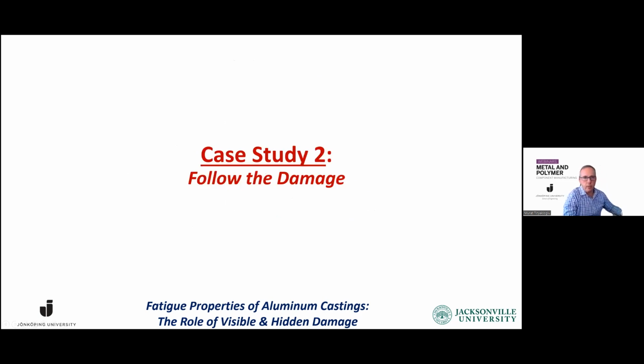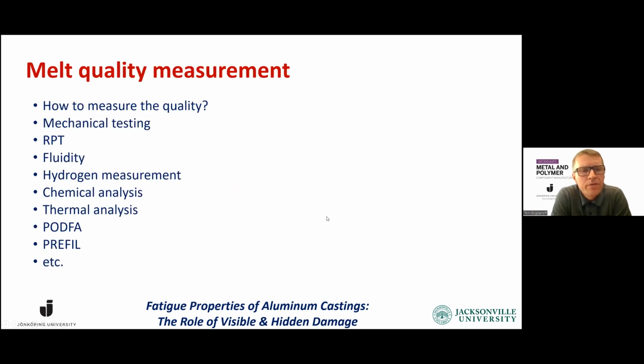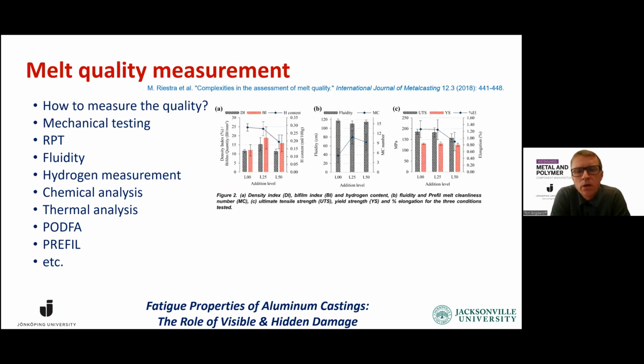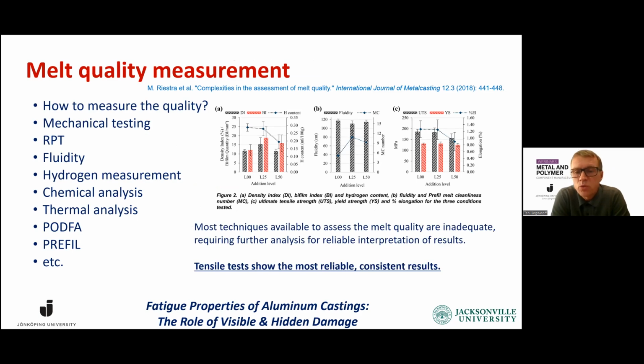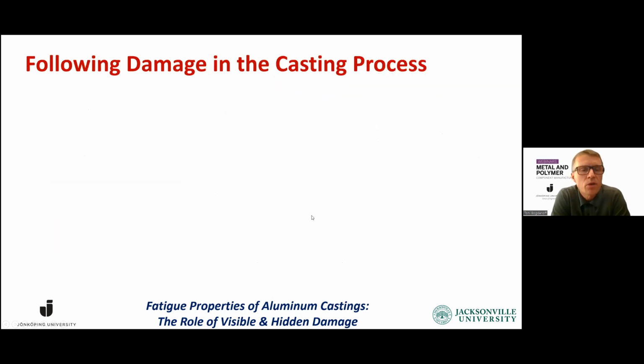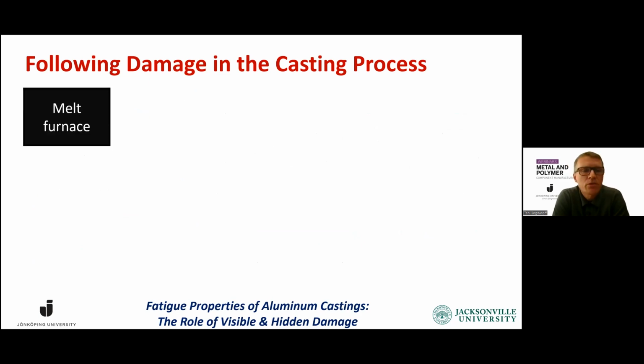With that said, let's have another case study where we follow the damage. Tony? Yes, and we start with how do we actually measure the quality. We have a lot of different techniques, and together with some colleagues of mine, we published a paper where we tested as many as possible. If you want to read more about this, the paper is published. But the finding is that the tensile test is the most reliable test that gives results that we can trust. And now we also did the same, together with RPT and tensile test, to actually follow the damage in the casting process in a foundry.